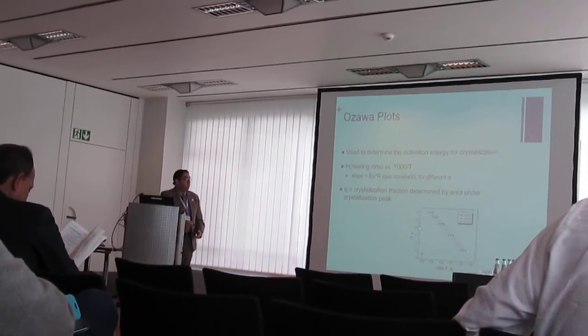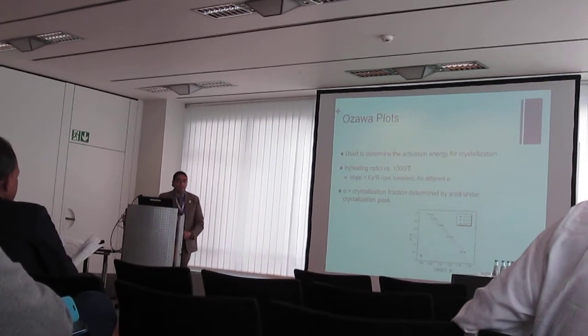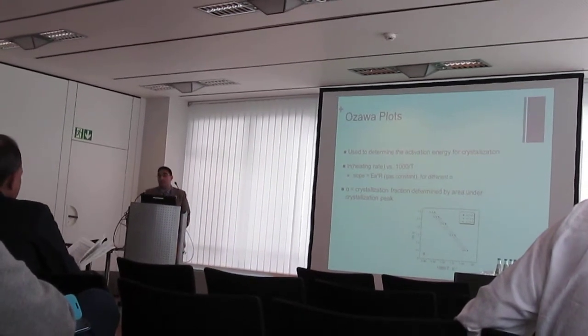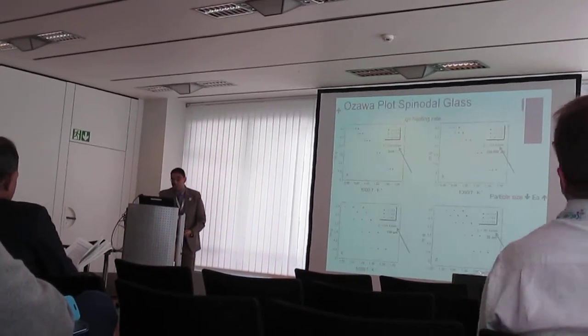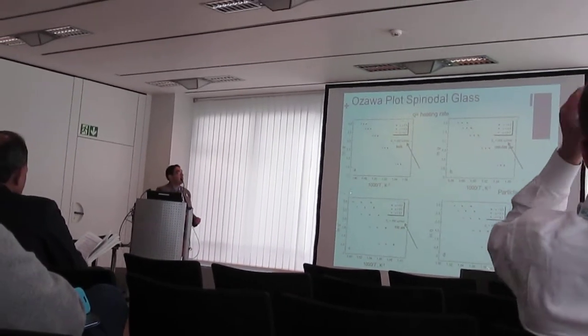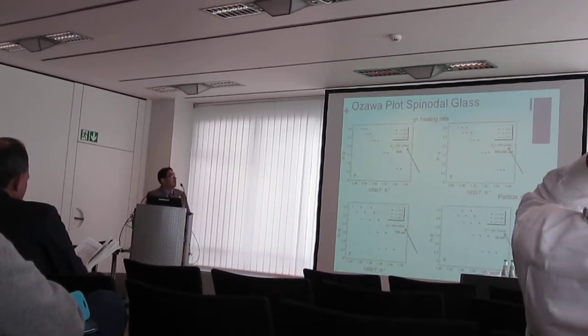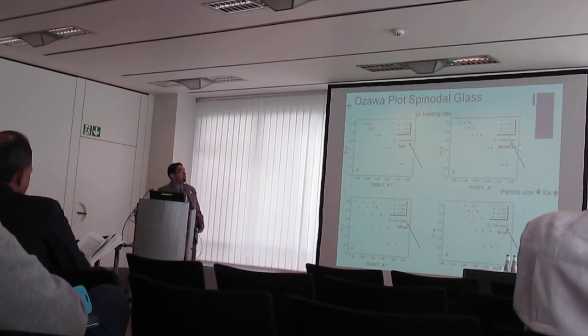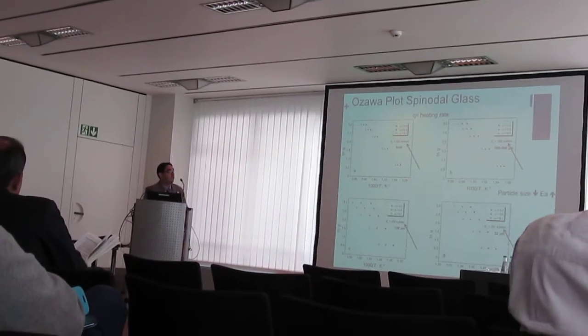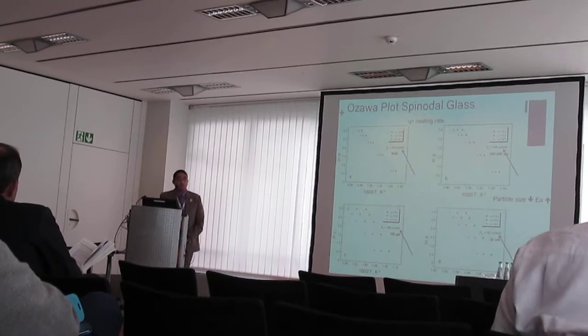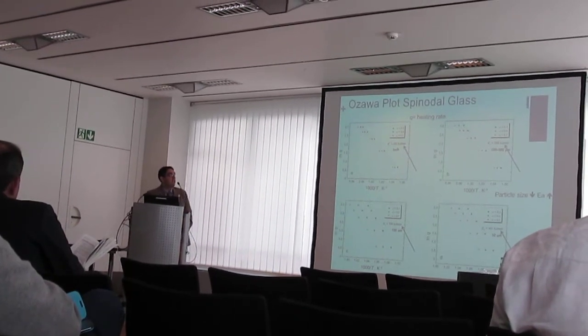Once we average the slopes and divide by R, we can get an average activation energy of crystallization. This slide shows the 4 different particle sizes, the bulk, 300 to 500 micron, 150, and 32 micron particle sizes for the spinodal glass.